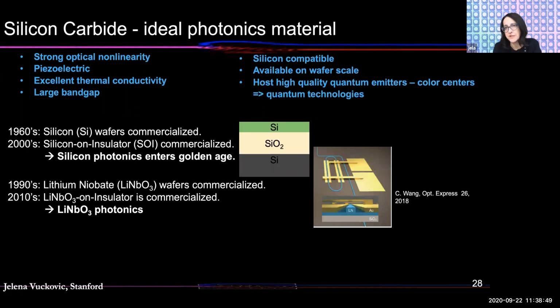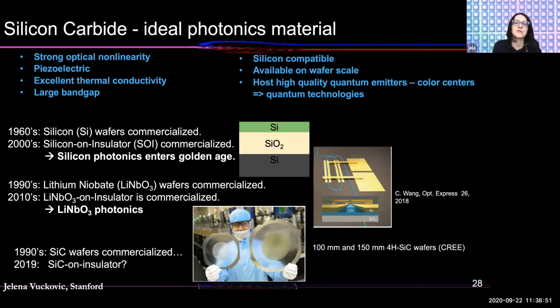The only problem with silicon carbide when we actually started working on this was that we didn't really have access to silicon carbide on insulator with high purity, which is what you need in order to make photonics, right? And if you are working on silicon photonics, you probably know that silicon on insulator wafers were commercialized about 20 years ago, and that was around 40 years after commercialization of silicon wafers. And after silicon on insulator became accessible, that's when silicon photonics really took off, because you need this thin film of material where you can guide light and build all the photonics.